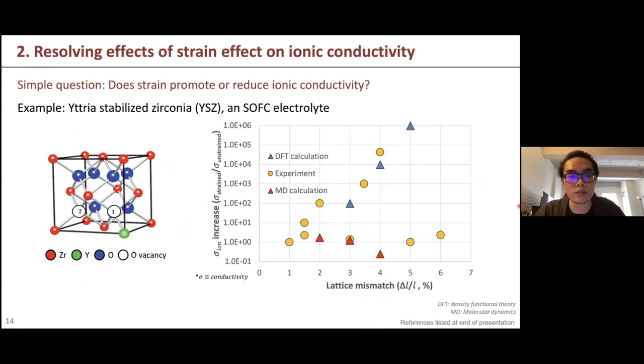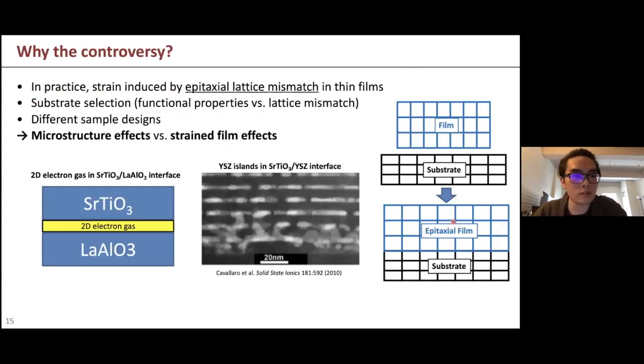So as you can see here, I'm showing a simple example using yttria-stabilized zirconia, YSZ, as an SOFC electrolyte. This is basically the conductivity increase between strained and unstrained samples. It includes both calculation and experimental studies. You can see that it can basically be divided into two branches. One group of people say, hey, it's very good, it's very promising. And the other group say, no, it's useless. So why do we see this controversy?